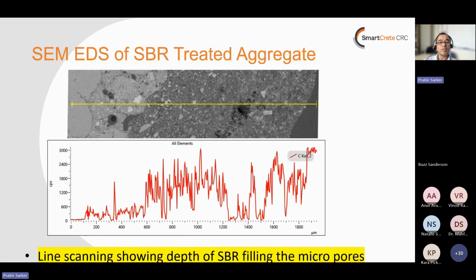And again, Riyadh has done this line scanning to see up to what depth this high content of carbon could be found, showing this is an indication that SBR latex has penetrated to that depth. This is in microns from the surface of the aggregate inside. So we can see it can go to a certain depth within the adhered mortar, which is evidence that it can improve the properties, and that is the reason why we see some improvement in the compressive strength and the pore filling effect, eventually improving the volume of permeable void and RCPT.